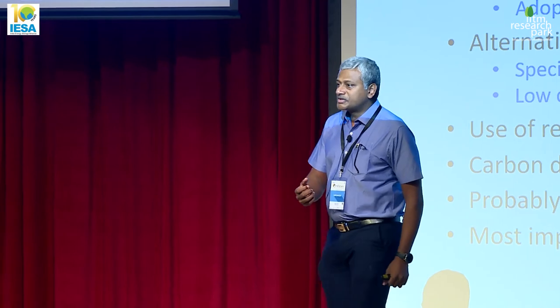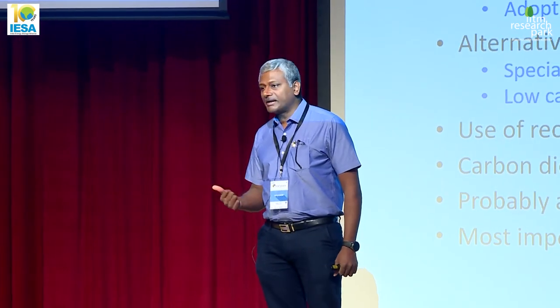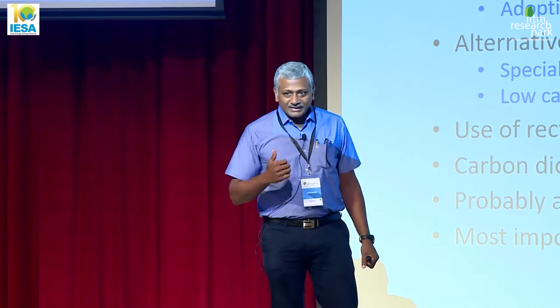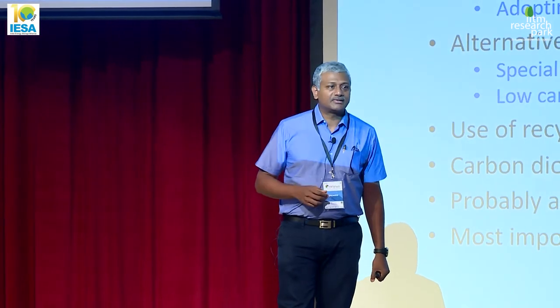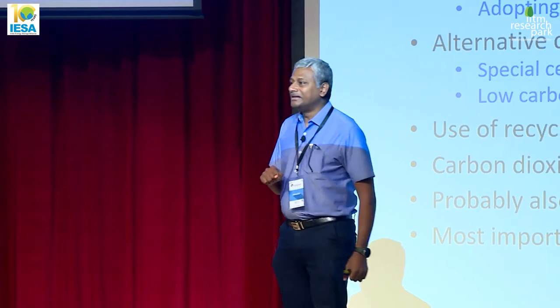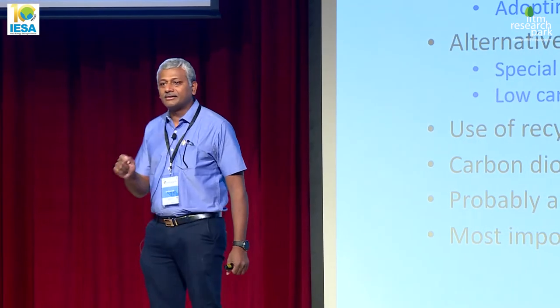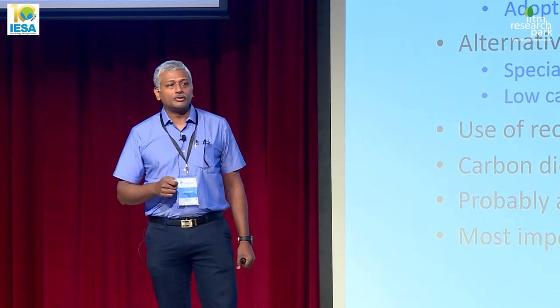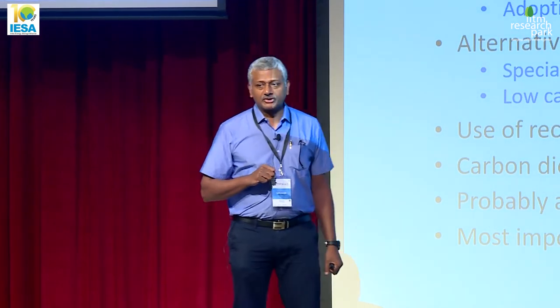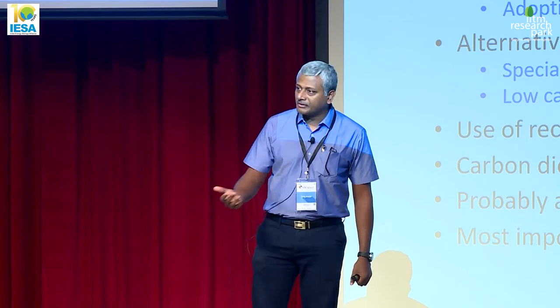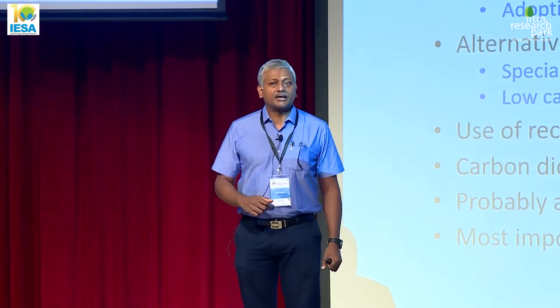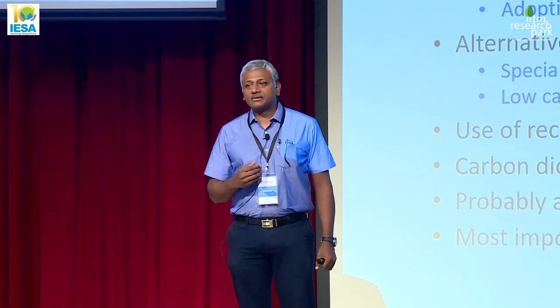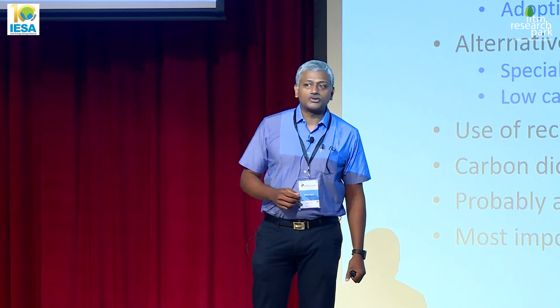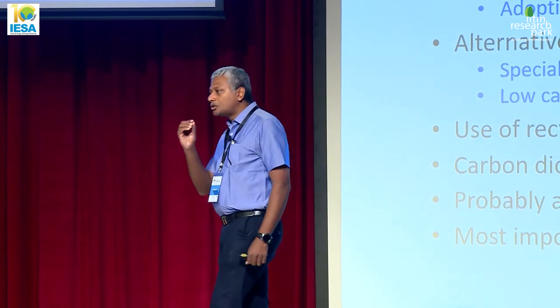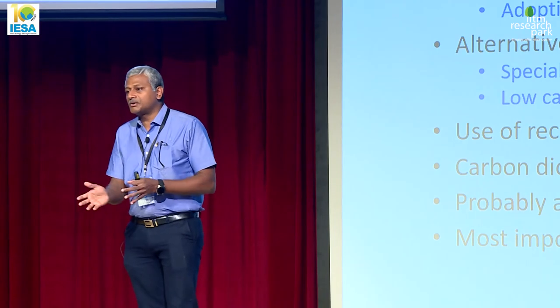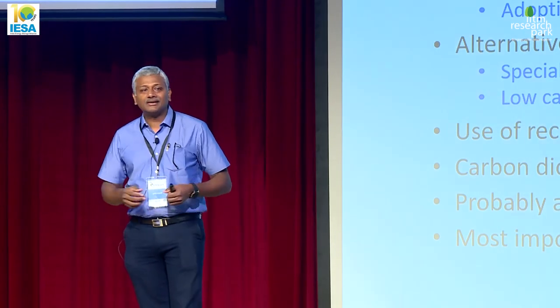Okay, the tools which are available to calculate these impacts are, again, European. And the data that we try to fit in is Indian, which usually doesn't really work out well. So we really need to collect this data from our cement plants and get the real data for energy and CO2 evolution during the different phases of cement manufacture. And that data is now available thanks to a lot of effort that has been put in by researchers in our group. We have actually got quite a bit of data from several cement plants. We hope to increase the range of data that we are collecting to really assess the true impact, rather than just saying that, okay, reducing cement by putting this is enough. We need to get the real picture here.